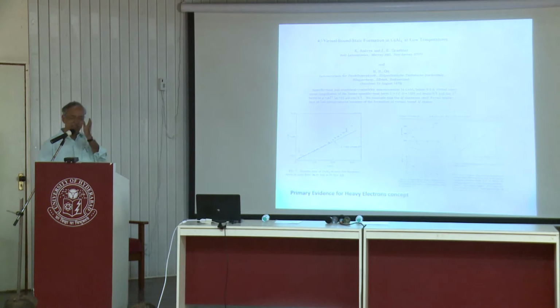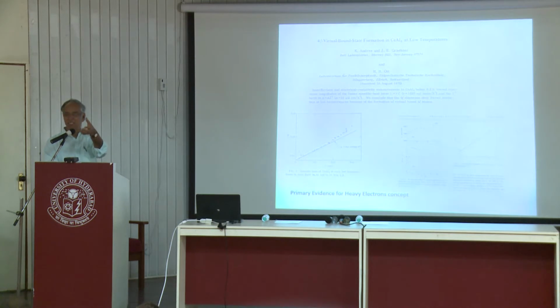In condensed matter physics and solid state physics, those who have studied, take a simple metal. There's a correlation between the electronic contribution to heat capacity, the magnetic susceptibility, and the electrical transport. There are coefficients involved, there's a ratio. So they tried to look at the ratio of the corresponding terms in susceptibility and the corresponding terms in resistivity, and they found even those terms are really enhanced. I don't want to go into the details. You could find that there is a susceptibility here. At high temperature, you have a strong local moment, as if it is magnetic. The 4f electron is strongly magnetic. But as you go to low temperature, you are losing that magnetism. It looks as if it's non-magnetic.